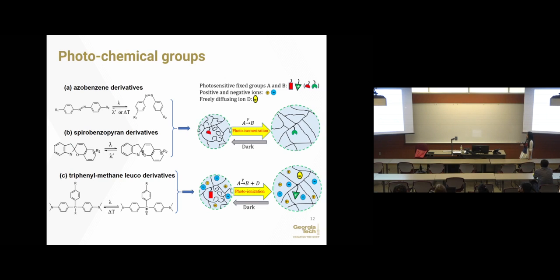That will drive the solvent to come in and out. So macroscopically, you will see this swelling or contraction of the gel. You can use that as an actuation mechanism and so on. And for this molecule, it actually is more interesting. When you shine light on, this bond is opened up, generating two separate parts of separate charges. So we denote it as the red one here. When you shine light, it becomes two separate parts with opposite ions.